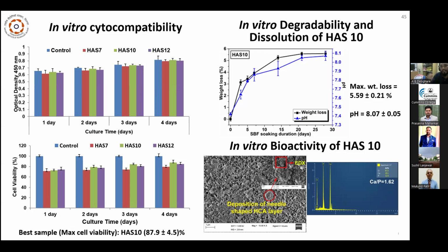And then, an in vitro biodegradability and dissolution test was also performed, basically to observe the weight loss of the prepared sample, where the sample is immersed in simulated body fluid for 28 days, and it shows that the maximum weight loss is 5.59 ± 0.21%. Then an in vitro bioactivity test is performed to see whether apatite is formed or not.